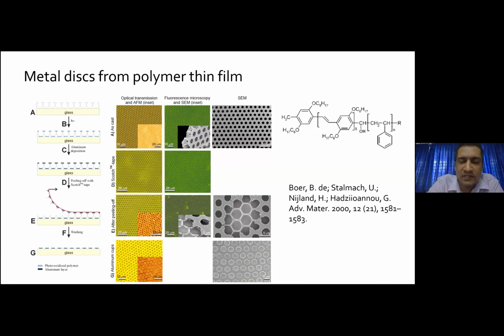Now, once you have this kind of polymer, and this polymer is coated as a thin film, you allow it to take the breath figure pattern, and then you do the UV curing in the presence of a curing agent. And then the next step is a very interesting idea: you take a scotch tape, keep it on top of the thin film, and then peel off the scotch tape.